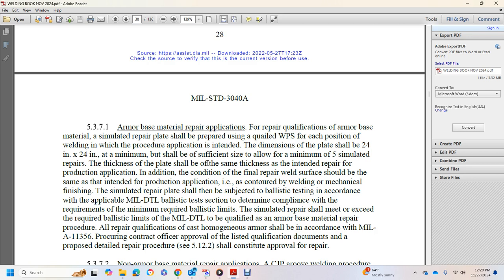ballistic testing section to determine compliance with the minimum required ballistic limitations. The simulated repair plate shall meet the requirement of the ballistic limit in the MIL-DTL, qualifying the armor base material repair and procedure. All repair qualification of homogeneous armor shall be in accordance with MIL-A-11356.